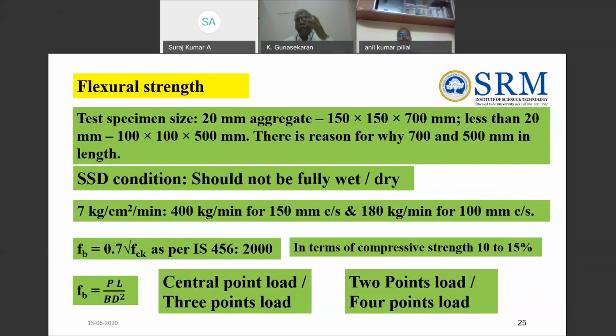ratio of 4. Because if the span to depth ratio is increased or decreased, then the flexural strength is getting altered. Similarly, the rate of loading application was also found to influence the flexural strength of the concrete very significantly. The strength increased up to 25% with increase in rate over the standard rate. Similarly, here also, I hope you understand why it is kept as 4. The reason is if the effective span to depth ratio is not 4, then the flexural strength will not give the exact value. That is why the standard specifies that ratio.